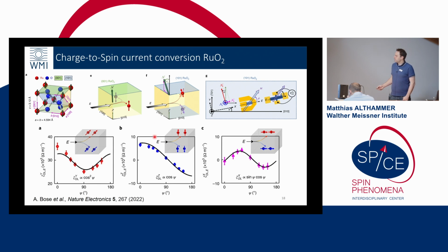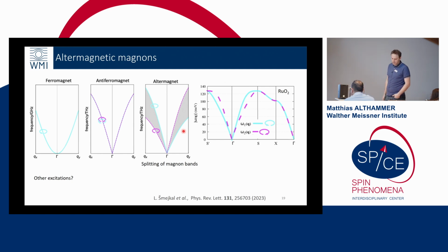But in ruthenium dioxide, you also have the possibility to get spins that are oriented in this fashion, that point out of the top plane, which you would not expect. This comes from the fact that now you can also control the orientation of your spin via the Néel ordering parameter. So taking different orientations will allow you to selectively get to this. And with this nice torque, you could think about switching perpendicular magnetic anisotropy structures with that system, and it's a very efficient one.